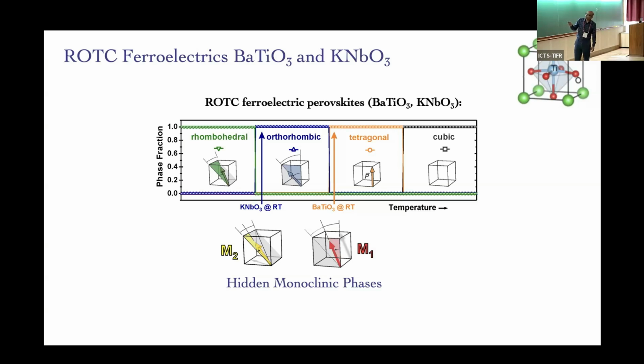Rhombohedral, orthorhombic, tetragonal, cubic, this is the classic equilibrium phase diagram, right? And barium titanate at room temperature is tetragonal, whereas potassium niobate is orthorhombic. Now it turns out that between here and here, there is a metastable state, which is monoclinic. So here, cubic, there is no polarization. That titanium is right smack in the middle. So there's no net polarization. Center of positive and negative charge are the same. But if it pops up or down a little bit, it develops a polarization in the vertical direction. If it pops along the face diagonal, then it develops along the face diagonal. And if it pops along the body diagonal, then it develops the rhombohedral phase, right? So these are the various phases.